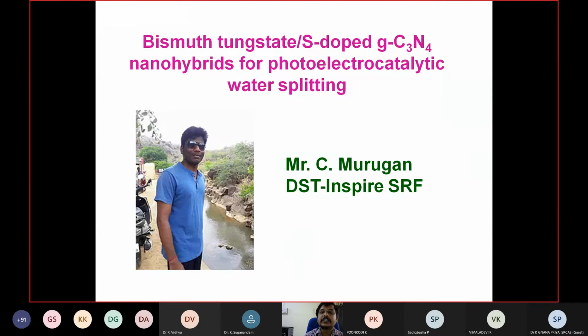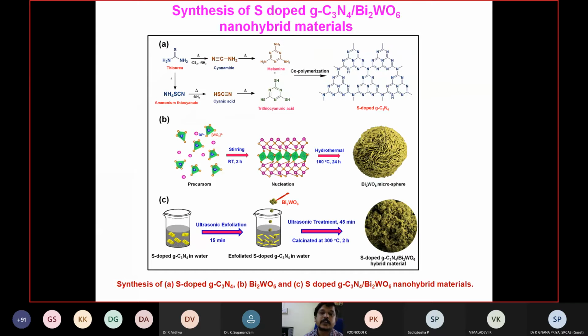Okay, so let me see the other system developed by the same student. In this work, he synthesized bismuth tungstate and sulfur-doped graphitic carbon nitride heterojunctions for photoelectrochemical water splitting. For this, he took thiourea and subjected it to pyrolysis and polymerization. Finally, we got the sulfur-doped graphitic carbon nitride.